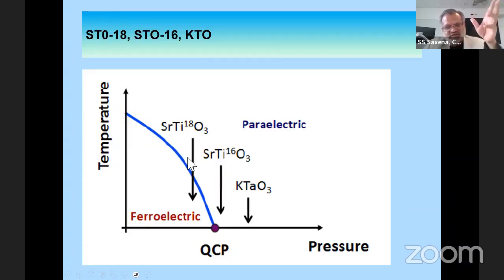So conceptually, normal strontium titanate, oxygen 16, sits at the quantum critical point. Naturally, the one that you can buy or you can grow. If you make oxygen 18, it's ordered at 30 Kelvin, as I showed you. But if you look at the properties, for instance, if you were to push it by using another control parameter, let's say pressure, you find that it looks more like potassium tantalate at high pressures, further away from the quantum critical point.